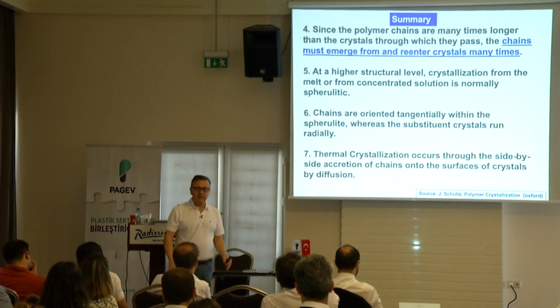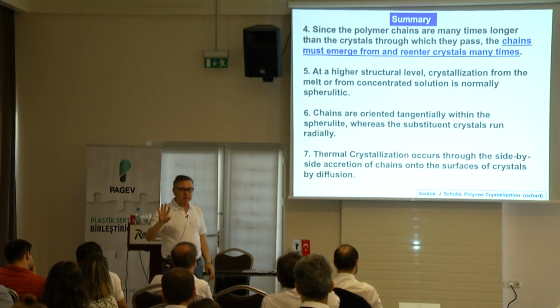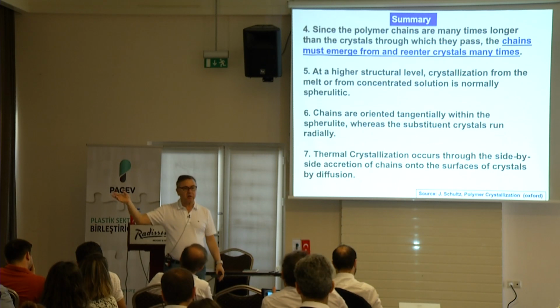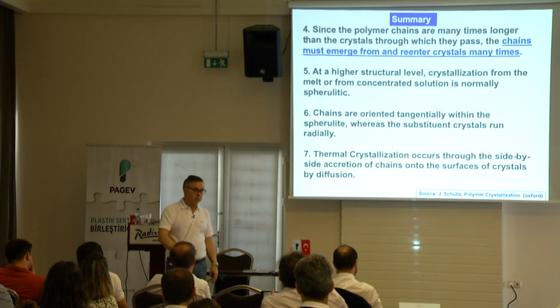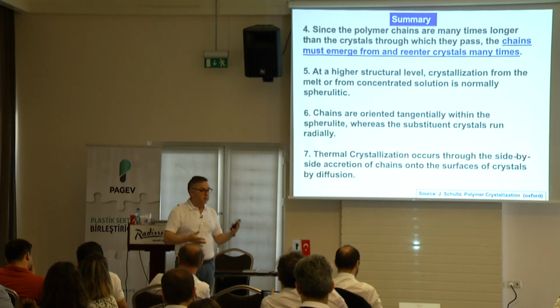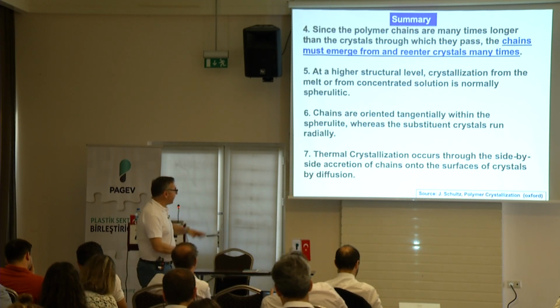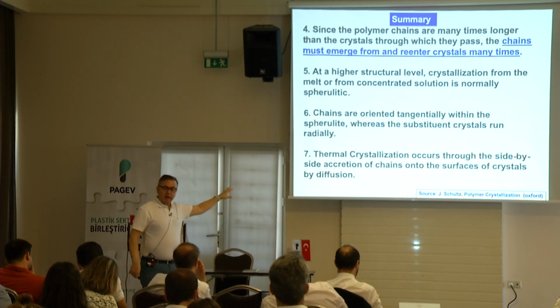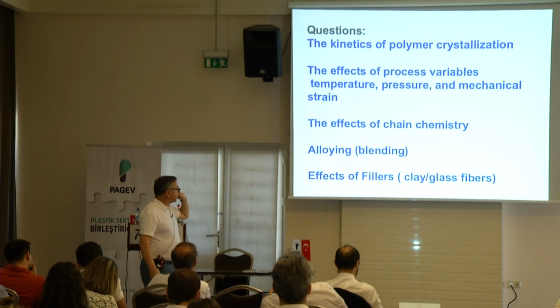So thermal crystallization is controlled by the viscosity that controls the diffusion. Molecularly, it's not totally independent, because if you reduce the molecular weight, viscosity goes down too. So that's sort of related. Keep that in mind because that's going to come back to us when we start looking at the processing of the material.